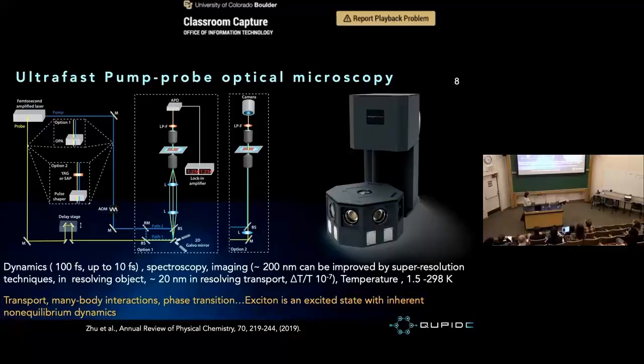And more importantly, now we can actually do these measurements at low temperature. Of course, it's not nanokelvin, but these are in a cryostat, so we can do this measurement at a temperature as low as 1.5 Kelvin. The key to the success of this measurement is that you need very high temporal and spatial precision, with high signal to noise. And the way that we track where these excitons are is using a method called pump-probe. So we have two ultrafast pulses.